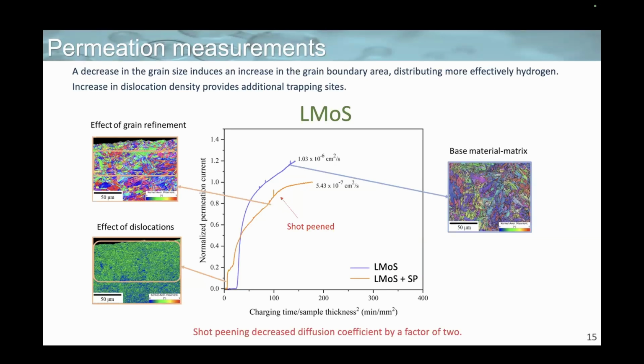The question is, what is the reason behind this? And we might ascribe it to 2 possible reasons. First one is that we have a decrease in grain size, which consequently induces increase in the grain boundary area, and then the hydrogen is distributed more effectively. And second possible reason is that we have increase in dislocation density, which provides additional trapping sites.